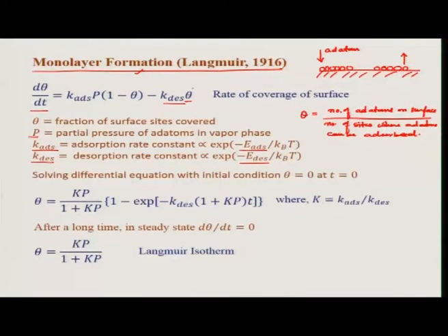So, it depends on how much is the fractional coverage, while on the other hand adsorption depends on the empty sites, 1 minus theta, and what is the partial pressure of adatoms in the vapor phase. Okay. So, the rate of change of fractional coverage will be given by this expression. Now, this is a differential equation which can be solved with an initial condition such that at time equal to 0 there was no coverage at all.